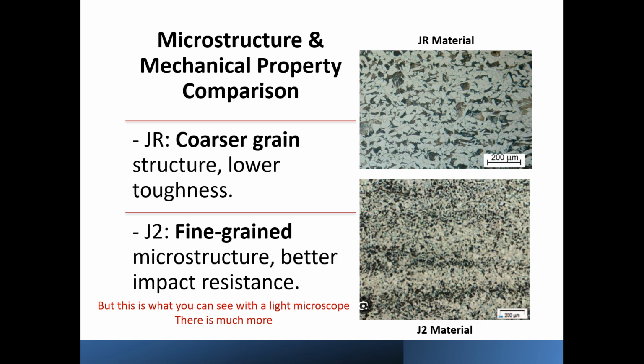So for those of you who are not metallurgists today, this is the sort of image that you get under a light microscope after mounting a sample in resin, grinding, polishing down to 0.25 microns, and etching it with some nitric acid. And it brings out what we call the microstructure, which I suppose we could compare to a person's fingerprint. It's what the material looks like under the microscope.